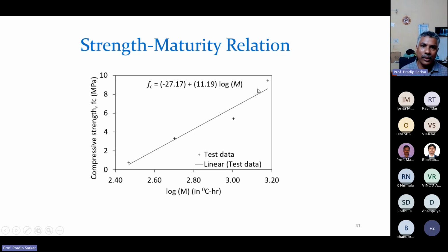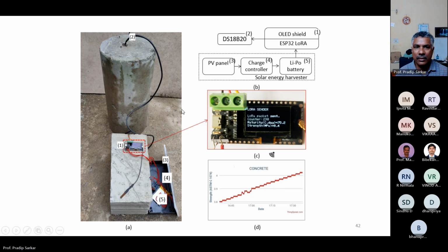And then we can do a plot of the test data at different ages and maturity. We got 1, 2, 3, 4 points, and from there approximate values of A and B are calculated. So f_c is equal to this much megapascal plus this much megapascal times log of maturity. That relationship is per the ASTM method. Now you can see all the information coming here. Maturity is 75.2 degree centigrade days, and strength is 8.4 megapascal. Per the ASTM standard procedure, we can see how strength is progressing.